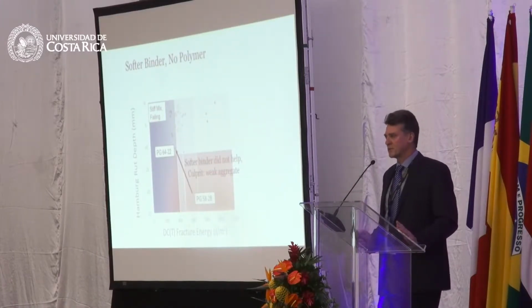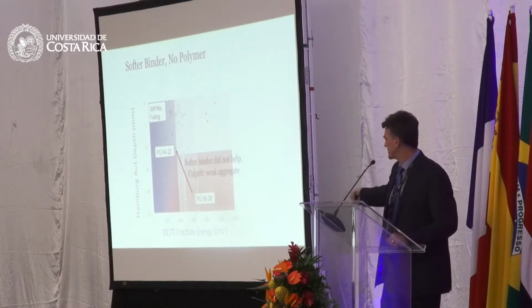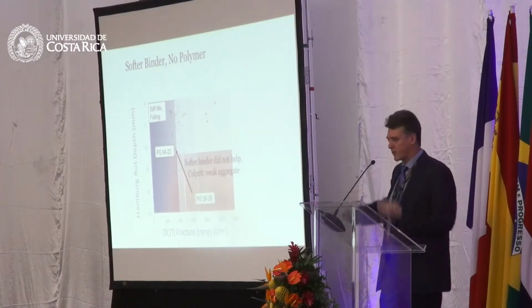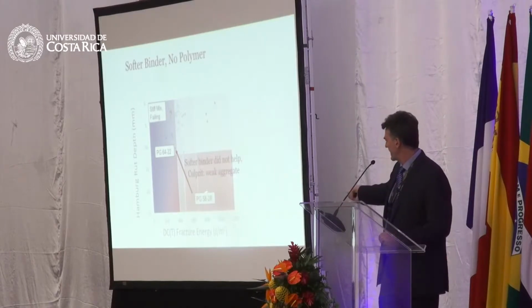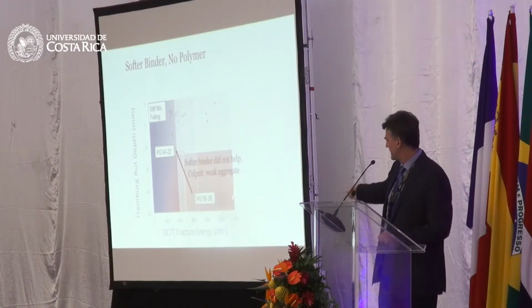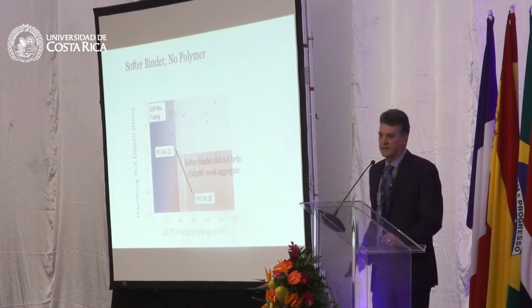Some interesting trends as we started to look at mixtures in Illinois. We saw that if you had a poor mix with a weak aggregate and a soft binder, it would fail in this hot zone here for rutting.